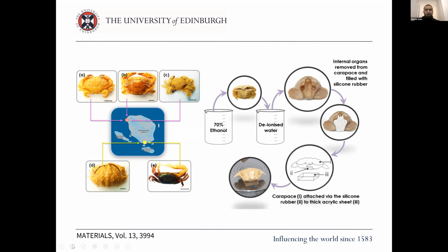Now, other marine organisms that we have studied, there are many, but other ones that we've looked at are crabs. And we've looked at crabs in several different ways and from several different angles. Recently, we looked at these 5 crabs that were collected by the Marine Study Group from Gajah Mada University on Wangi Wangi Island in Indonesia. And there are 5 different species of brachyuran crabs. What we did is we basically separated the shells from the crabs, removed the insides, cleaned them up, and then filled the insides with silicone in order to mimic the body structure. You don't really want to be doing cyclic impact tests on crab shells when the original body is there. Or maybe you do, I don't know, but I certainly didn't want to be involved in something like that.